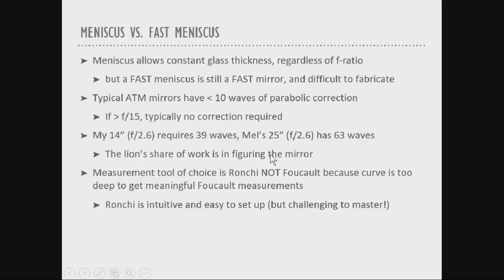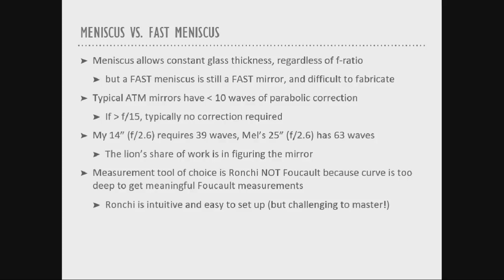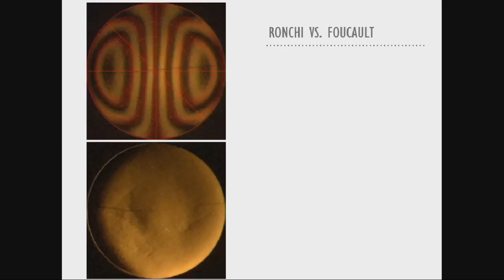It is difficult. The measurement tool of choice for this type of thing turns out to be the Ronchi test and not the Foucault test. Typically, ATMers use the Foucault test, up until relatively recently, when there are actually a number of really good alternative tests. Historically, the Foucault test was the ATM tool of choice. But the Ronchi test is much more appropriate here, because the curves are so steep that it's really difficult to get accurate Foucault measurements. And the Ronchi is a very intuitive and easy test to set up.